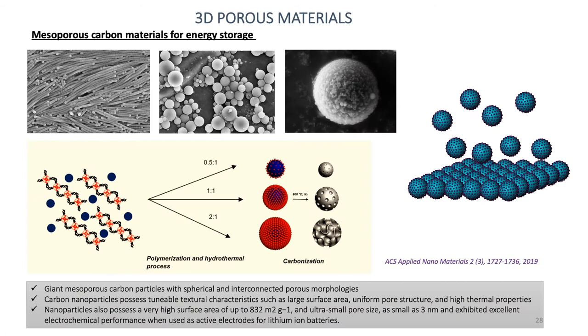We were also interested in structural features to make nanoporous carbon materials. In this study, we followed a soft templating process using block polymers. The target was to fabricate tunable carbon nanospheres with uniform porous structures. The pure block polymers exhibit rod-like features, but as the reaction proceeds, the long thread-like morphologies convert to form various spherical structures. We use these carbon materials as electrodes for demonstrating energy storage applications.